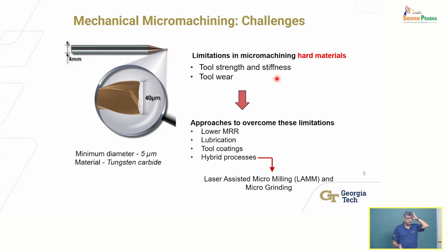And then where are these tools? They are very small to begin with. And you're trying to produce features on the order of hundreds of microns. And obviously the tolerance on those features, if there is a tolerance specified, would be one order of magnitude smaller. So any small amount of wear, especially if you're trying to make these types of features in difficult to machine materials, any small amount of tool wear can be a problem. You will actually deviate from the specified tolerance.